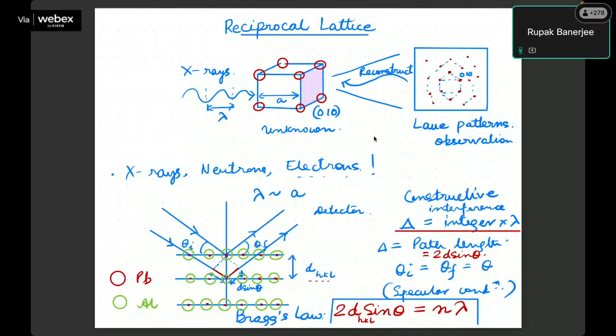You can also get this information from, say, TEM, transmission electron microscopy, or atomic force microscopy. But first of all, atomic force microscopy is a top probe, so you only look at the top surface. If crystal planes are not arranged in the top surface, you won't see them. You only see a morphology, right? Scanning electron microscope doesn't have the resolution to go up to lattices. But for transmission electron microscope, yes, you can visualize them very well.